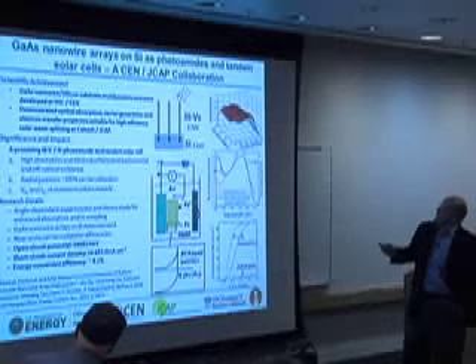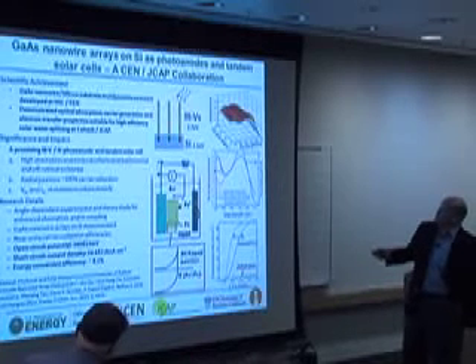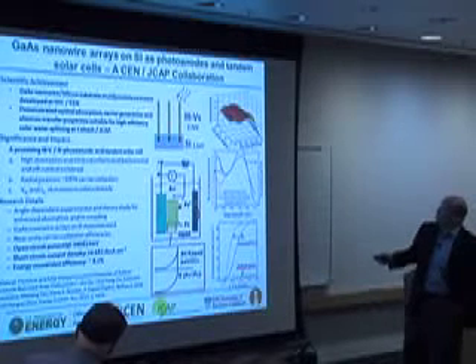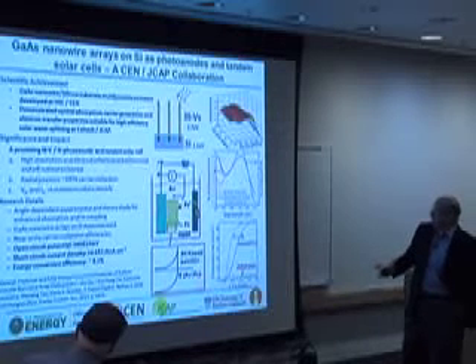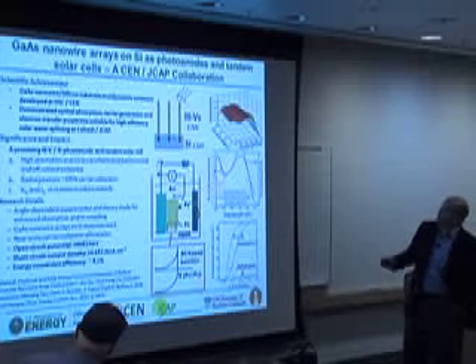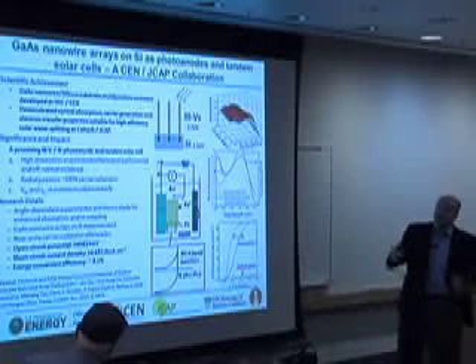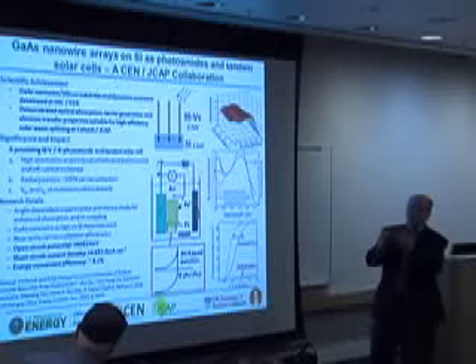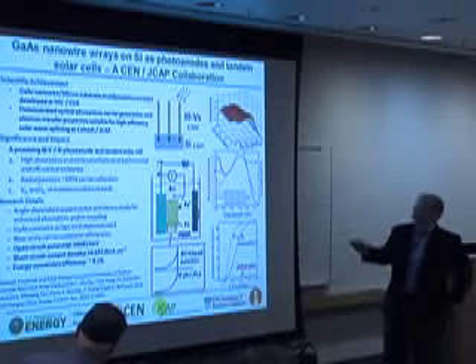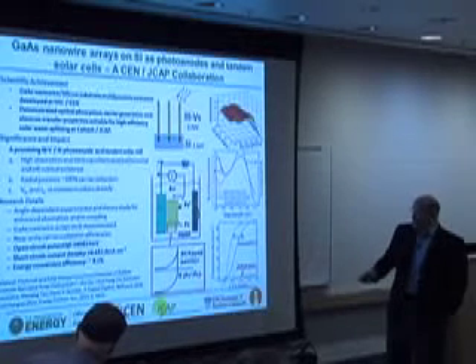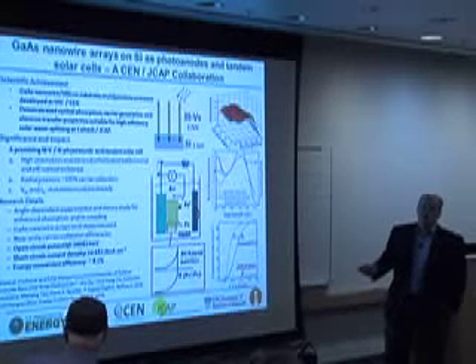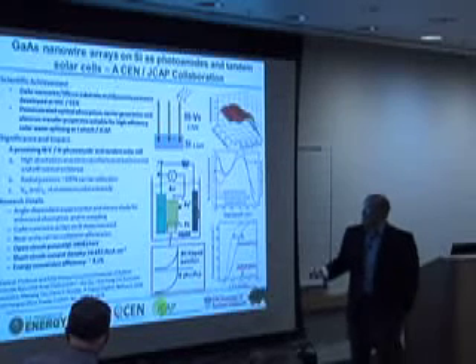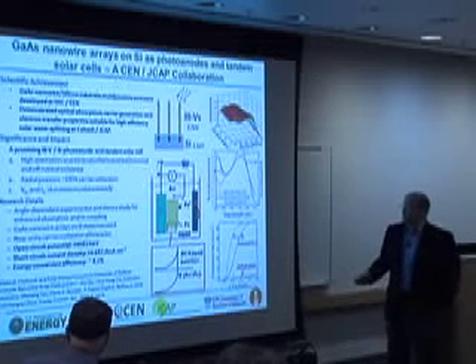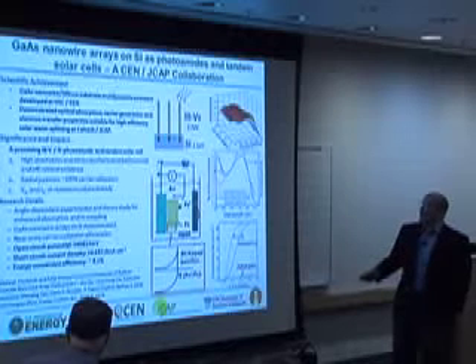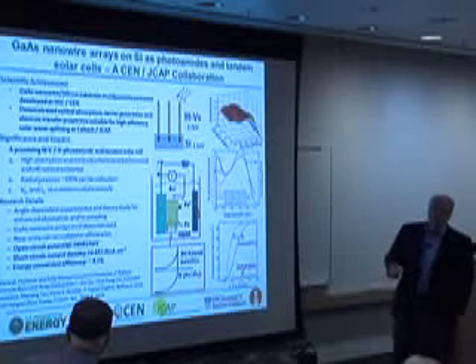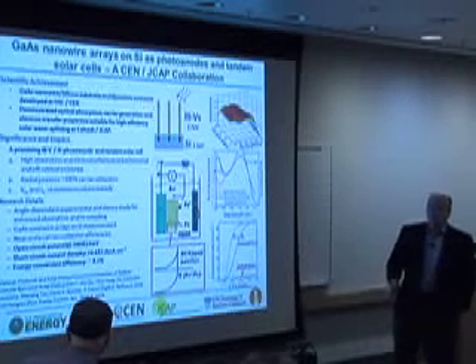And we haven't yet made a tandem cell out of the two, but what they have done is looked at the properties of these nanowires in a liquid solution, in a ferrocene kind of solution, and measured the photovoltaic properties. Now, in this particular case, since these rods are all surrounded by the liquid, it's essentially a radial junction, a Schottky barrier kind of junction between the liquid and the nanowire. And we've achieved conversion efficiencies of about 8% using those. That's still well away from our goal, but it's not bad. It's one of the best results for gallium arsenide solar cells. And the most important thing is that with this kind of radial core-shell design, we're getting short circuit current densities which are very close to what you'd expect in an air mass 1.5 solar cell.